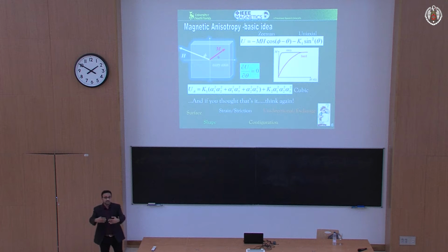If you take a hybrid material with the interface between two different materials, you can use the substrate or the strain in one material to control the magnetism in the other. This is well known, so you can use that also to tune the effective anisotropy. Configuration, I will give you some example of what configuration can play a role.